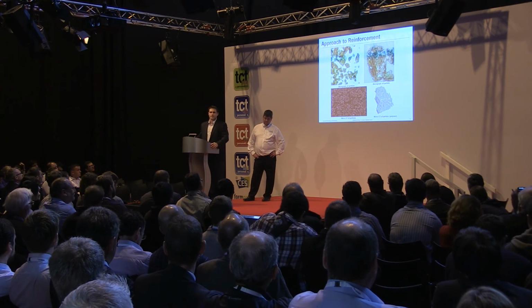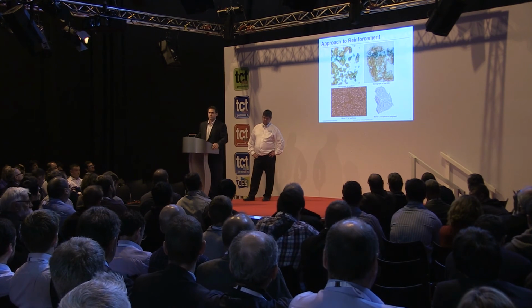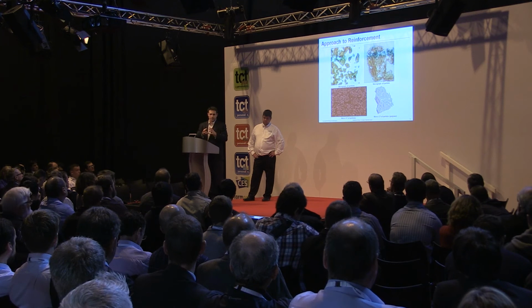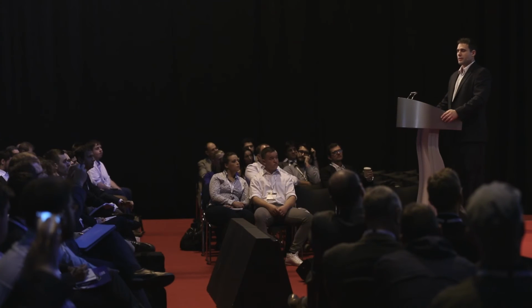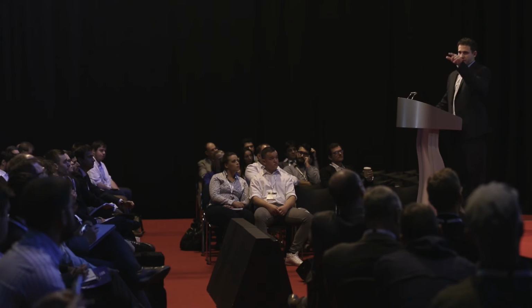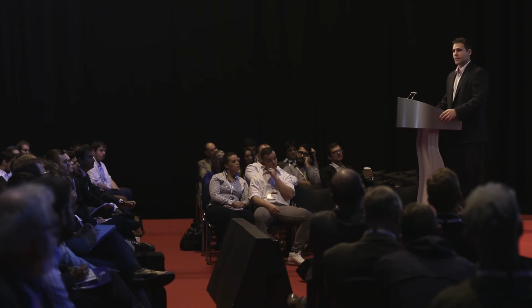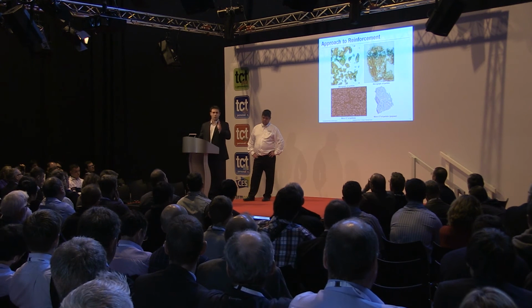The reason why we do that is that when you roll the material out, with a generally spherical particle, you get a generally isotropic orientation of your fibers, and your modulus and mechanical properties are commensurately isotropic. There's still a little bit of knockdown in Z because you still have stair stepping and layering in a powder-based process. So you get about a 10-15% knockdown that way, but that's close enough.